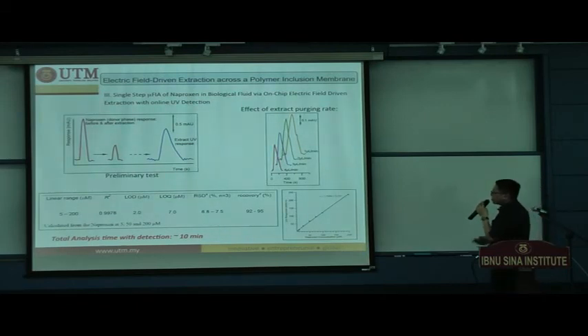So this is the summarized result using a purging rate of 3 microliters per minute. We were able to form a very linear calibration by injecting samples containing 5 to 200 micromolar of naproxen in human urine. The LOD is down to 2 micromolar, which is sufficient for clinical analysis, with a very good recovery from 92 to 95%. Most importantly, the time from sample injection to detection is only 10 minutes. So this is a very specific approach that only focuses on naproxen in human urine samples.